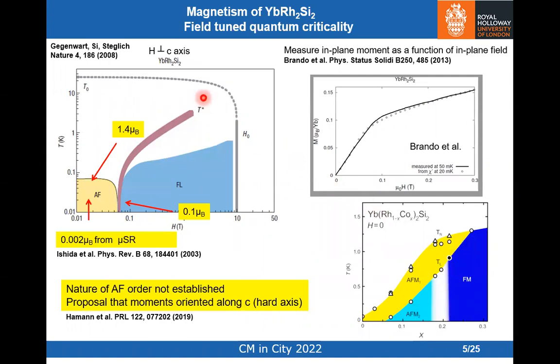So you're probably all familiar with the field-tuned quantum criticality in this system. This is the field being varied in plane. So in low magnetic fields, antiferromagnetic order develops below about 70 millikelvin. And according to mu-SR measurements, the ordered moment, the static ordered moment, is extremely small. It's only 0.002 mu B.